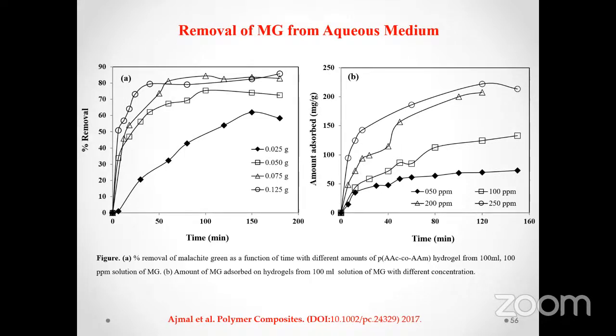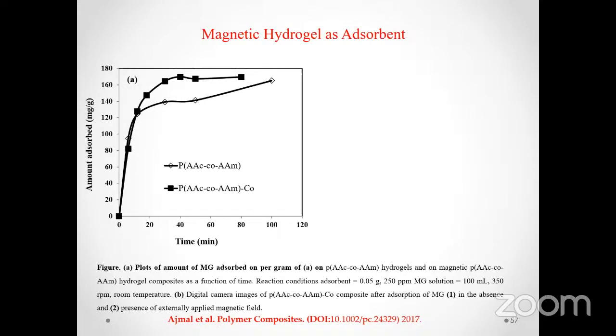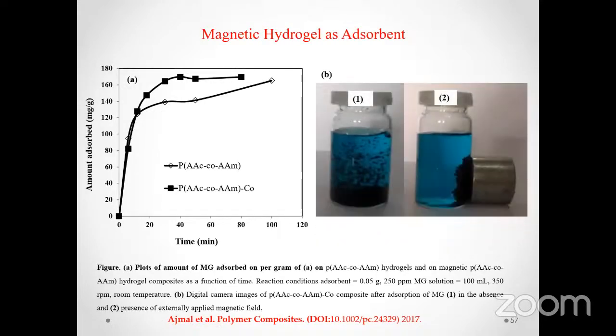The adsorption capacity of the hydrogel was also remarkable, that we have observed more than 80% removal of malachite green in this case. The magnetic hydrogel system was also found to be very effective, and the adsorption capacity of the hydrogel was also increased by the fabrication of magnetic nanoparticles, with an additional advantage of removing this adsorbent by applying the external magnetic field.